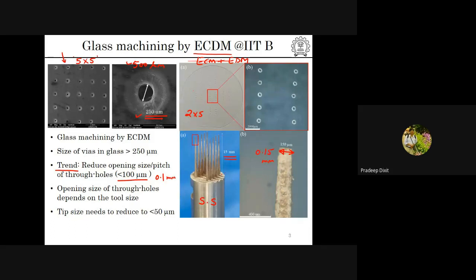Now, if you look at this picture of ECDM, if you want to create smaller holes, naturally you have to fabricate a smaller tool electrode. If you look at this dimension here, 0.15 is the tool size, which results in the formation of 0.25. It means that the final opening size of the through holes is always more than the tool size. So if you want to create 100 micrometer holes, the first thing is that you need to make a tool electrode having a size of 50 micrometer. And this is not a very easy task. The through hole size will ultimately be decided by the tool electrode size.